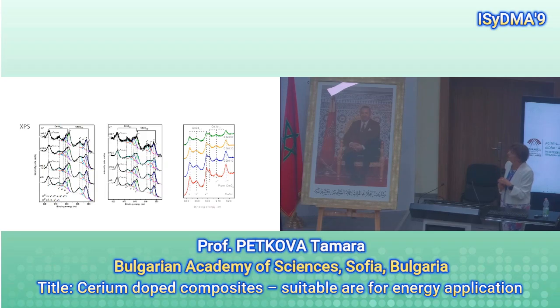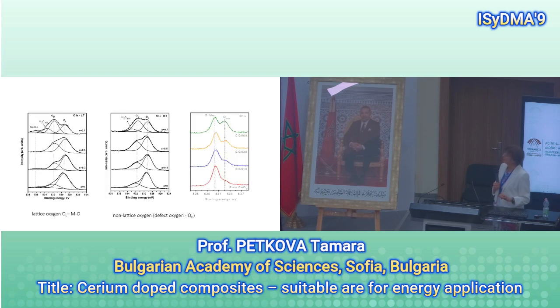Next study about the structure is the study with X-ray photoelectron spectroscopy. Here are presented the graphs of cerium. They are typical to cerium, with 6 main peaks that belong to cerium 3d, and these 6 peaks are due to the presence of cerium 3+ and cerium 4+. In order to calculate the amount of cerium 3+, we made a deconvolution of the spectrum and found that a small amount of cerium 3+ is obtained, which slowly increases as gadolinium increases in amount.